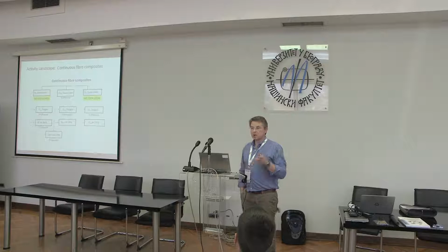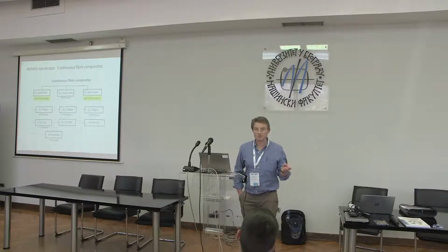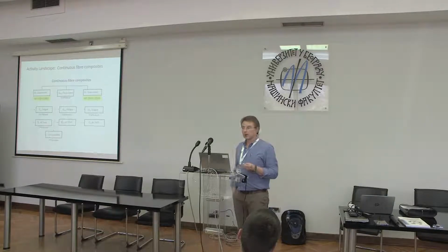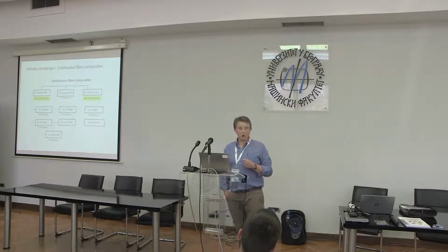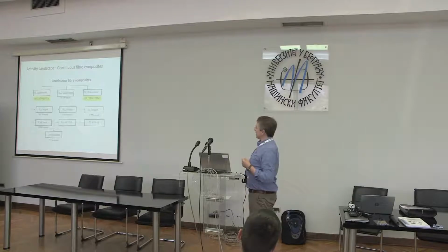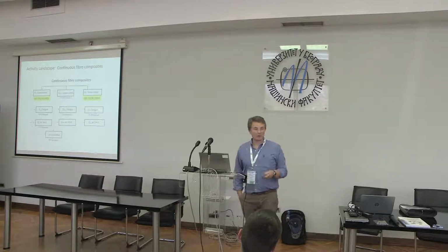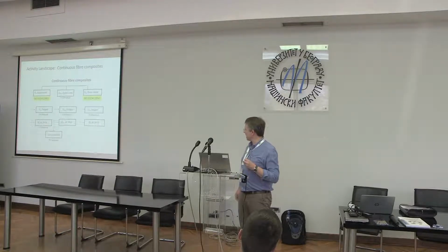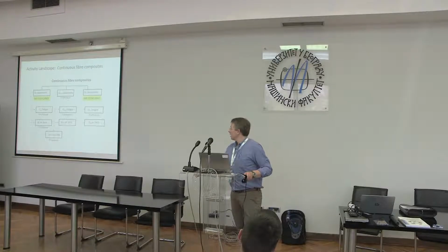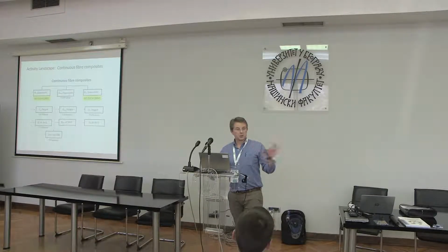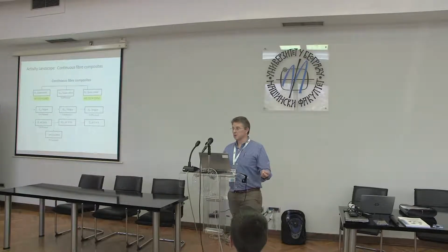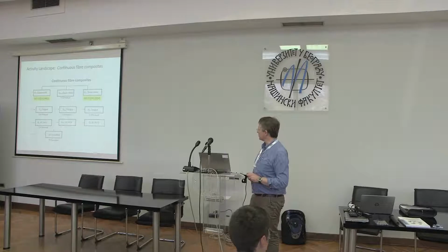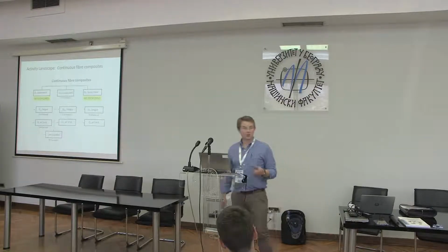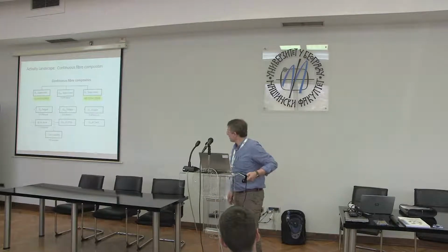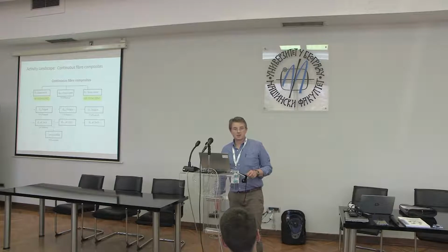Moving to composites, for the reasons we discussed a little bit before, we're interested in mode 1 and mode 2, and of course mixes of 1 and 2. You might ask about mode 3. There is some work going on in mode 3, but it's an area that the technical committee haven't got specifically involved in yet, so we've been mainly involved in mixes of mode 1 and 2. With those mode mixes, you can have the quasi-static situation where the crack is loaded slowly, the fatigue situation, where we've been developing fatigue protocols, and the high rate situation where you have a rapidly growing crack. So the fatigue and the high rate are all work areas.